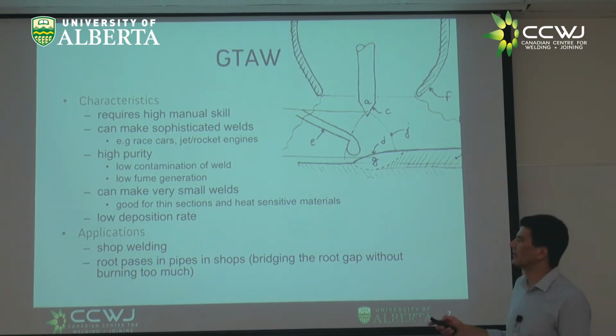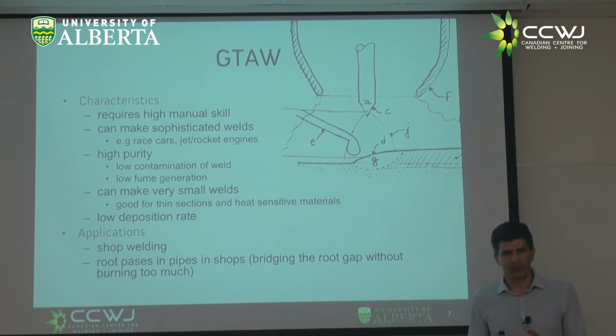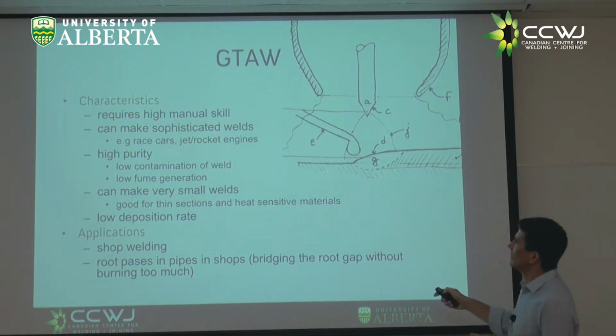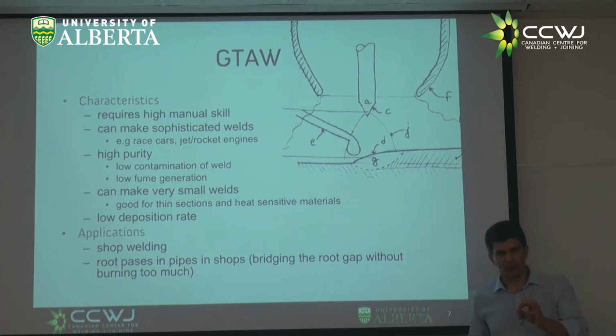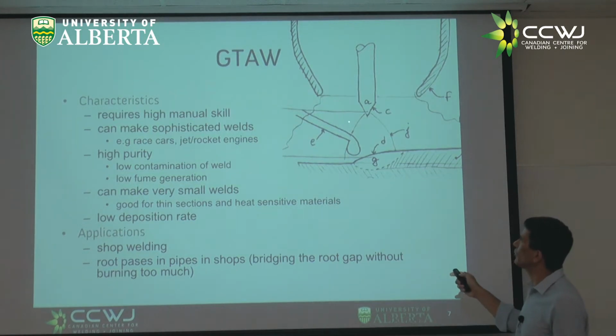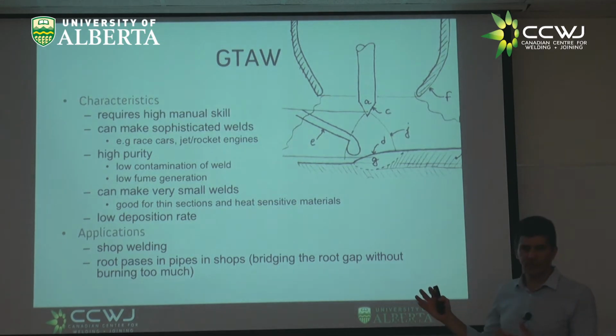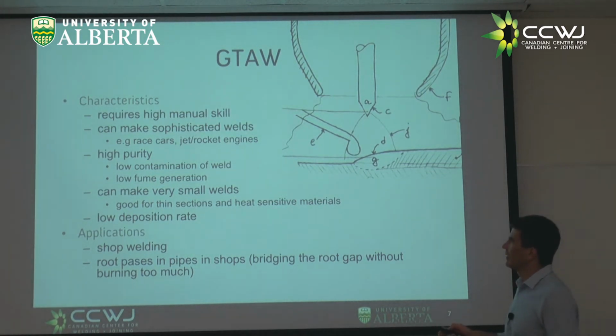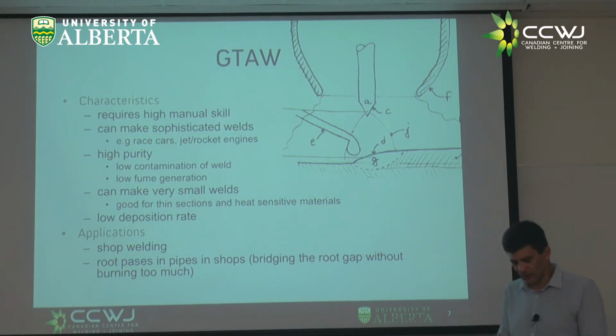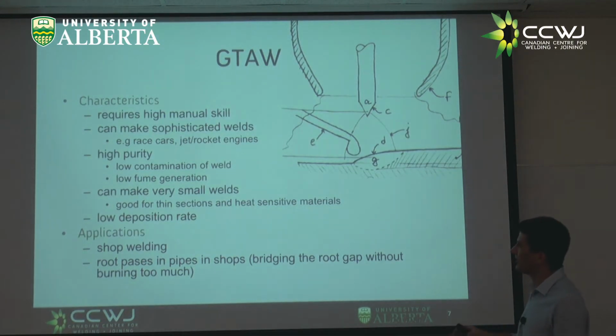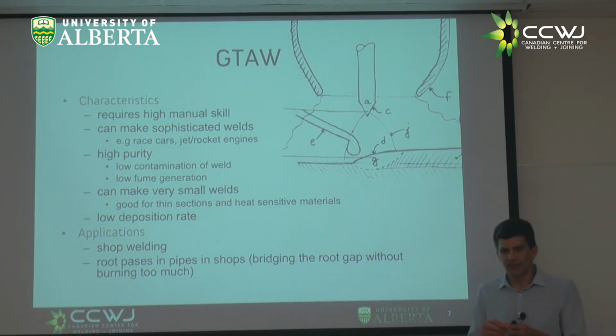Rocket engines, TIG welded. You can have a very high purity in here, and it is because everything is very controlled. You're not bringing a new wire, you don't have fluxes, you don't intentionally introduce any oxidizing component here. You're going to see in other types of welding, you do. It has low fume generation, so it's quite a clean and attention-oriented operation. You can make very small welds. So it's good for thin sections, heat-sensitive materials.